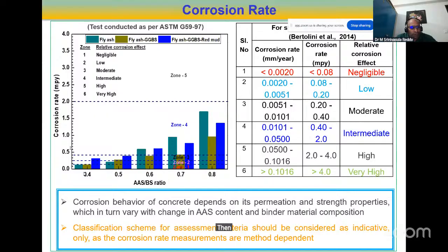Then only I can notice moderate to intermediate when the ratio is 0.6, 0.7 and 0.8. But if the ratio is below 0.5, like 0.5 or 0.4, you will have very low and negligible corrosion effect. This corrosion again depends on the permeation, as all you people know. This permeation usually influences the corrosion behavior.